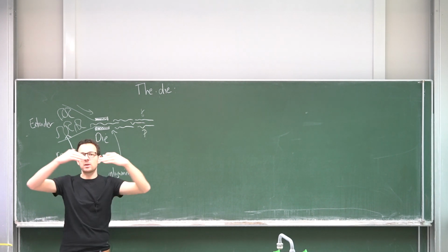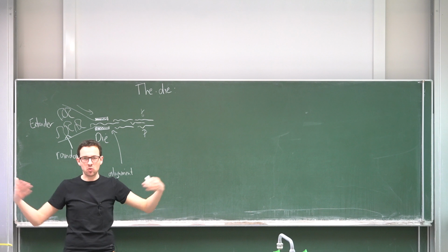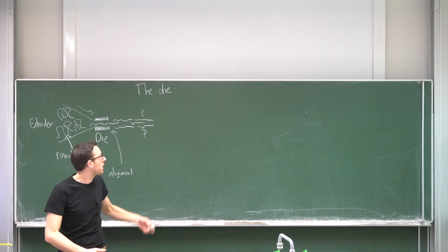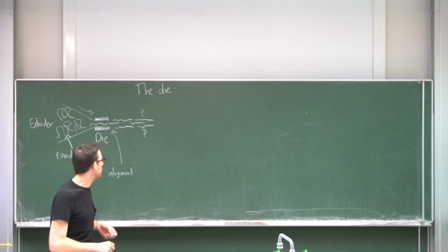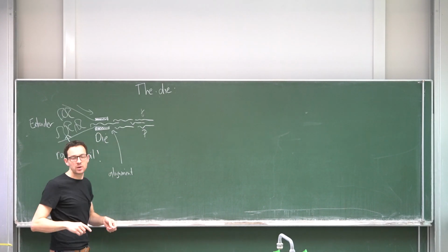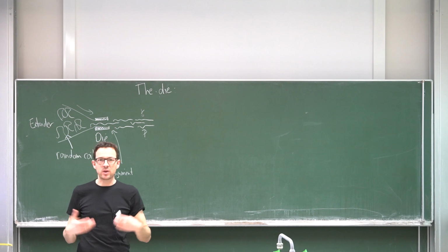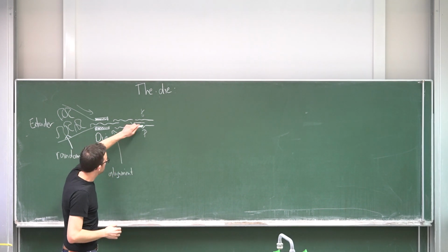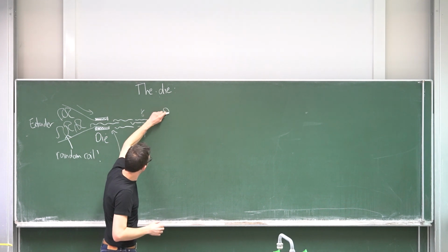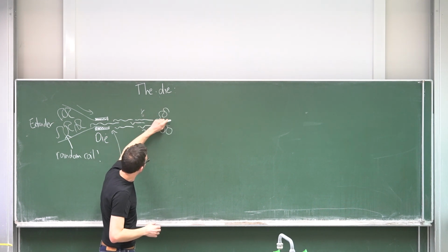I don't really like to be in this stretched out conformation, and entropy tells me to please go back into my minimum energy state, which is a random coil. So what they will do, pretty much directly after this external pressure is relaxed, is start to coil up again.